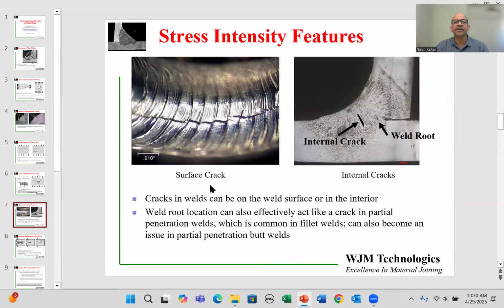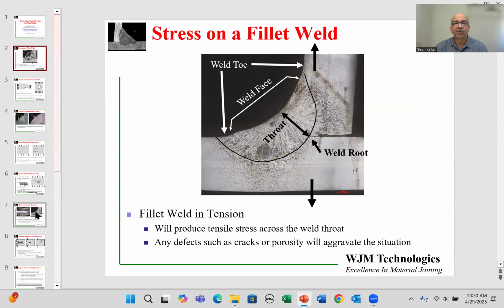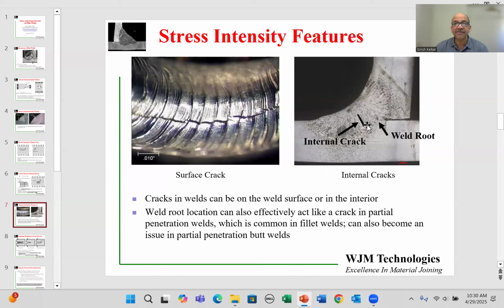Here I'm going to show you a couple of photographs. This is a surface of a weld. This is a linear weld, and you can see a surface crack over here. And here I'm showing you a cross section. Now this particular cross section is the one I showed you before. This particular one does not have a crack, but if it had a crack, for different reasons, and there are many other reasons for cracking, the crack would be somewhere inside and looks something like this. We also have the weld root, which is also effectively like a surface crack. We see a sharp point where the root comes to as a junction to the fusion zone, and it effectively also acts like a crack.